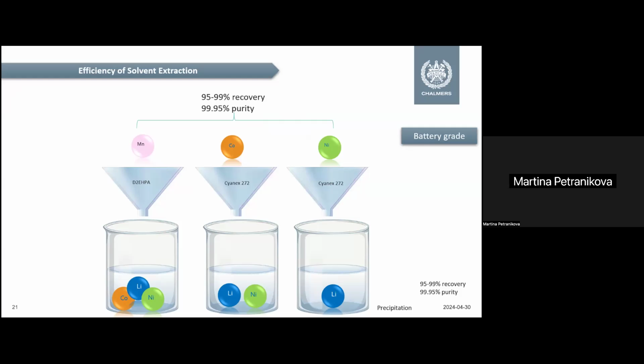And the purity is actually very high because it's a very effective method, and we can achieve battery-grade purity for these metals. And also the recovery is very high. And then usually lithium is just precipitated at the end, because if we remove all the transition metals, then in our solution we keep only the lithium, which then is precipitated. And the battery-grade purity is very high.